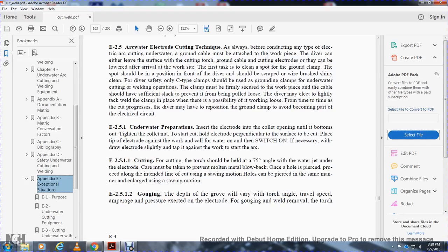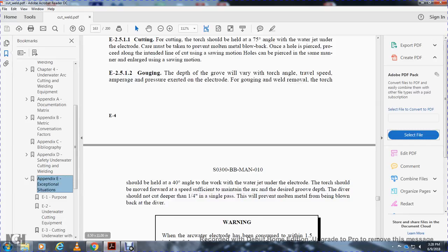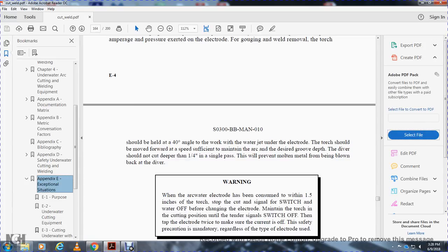2.5.1.2 Gouging. The depth of the groove will vary with the torch angle and the travel speed. Amperage and pressure are exerted with the electrode for gouging and weld removal. The torch should be held at a 40-degree angle with the water jet under the electrode. The torch should be moved forward at a speed sufficient to maintain the arc at the desired groove depth. The diver should not cut deeper than a quarter inch in a single pass, which will prevent the molten metal from being blown back to the diver.